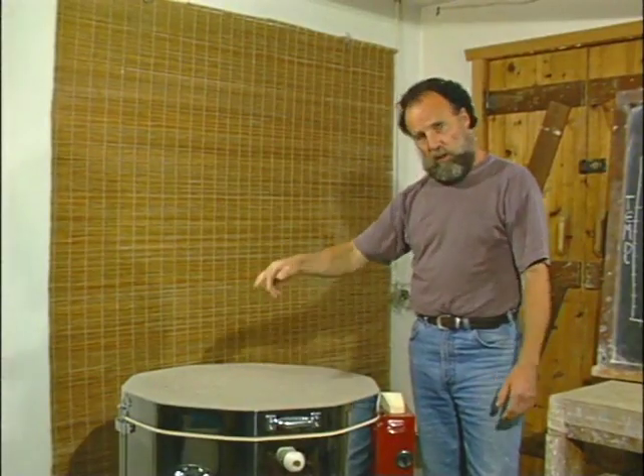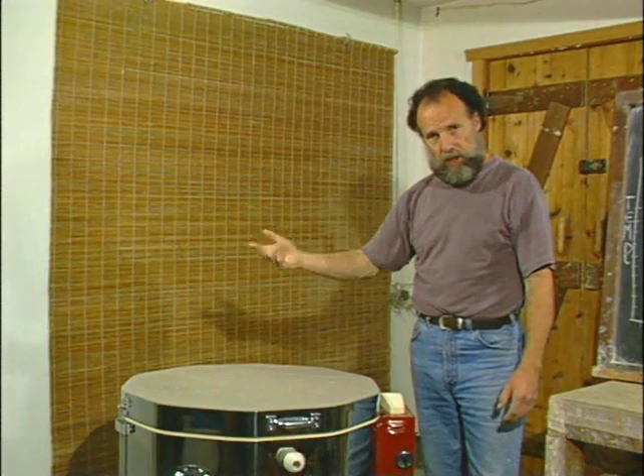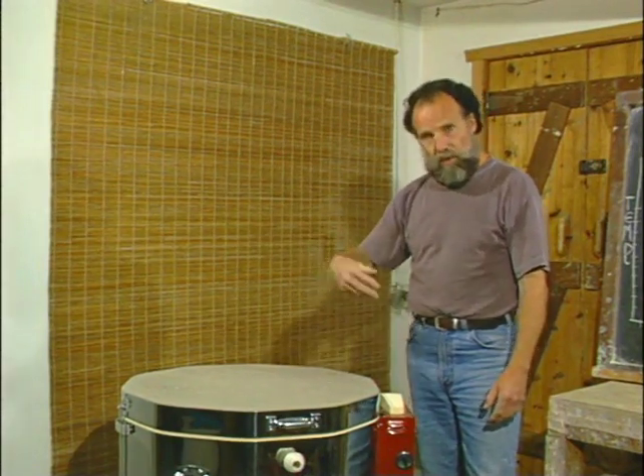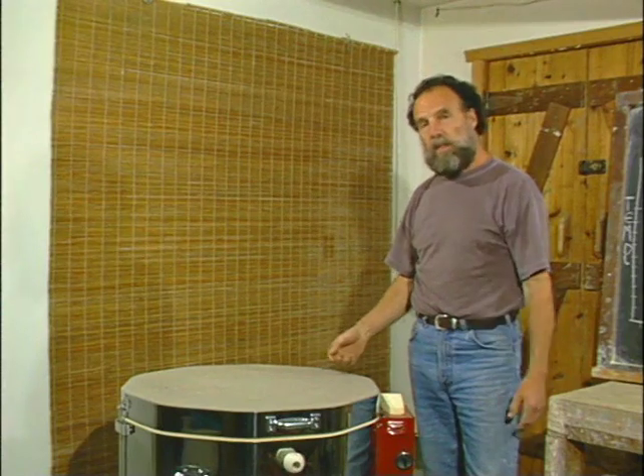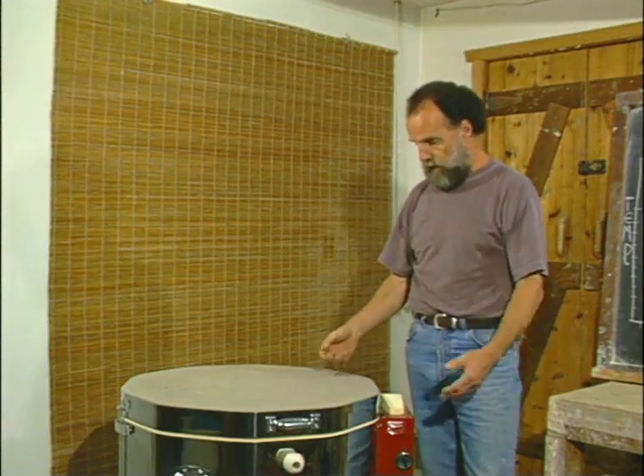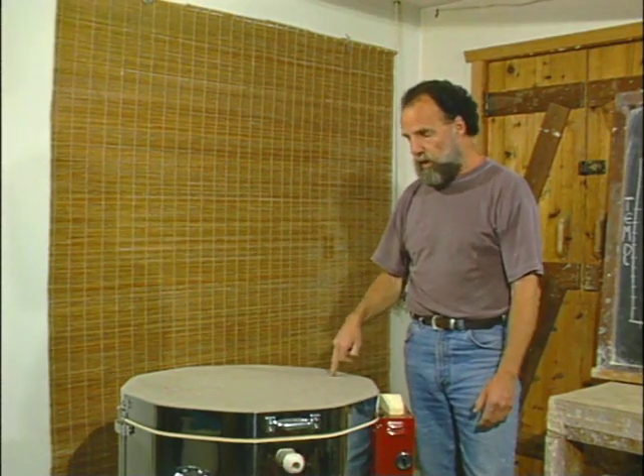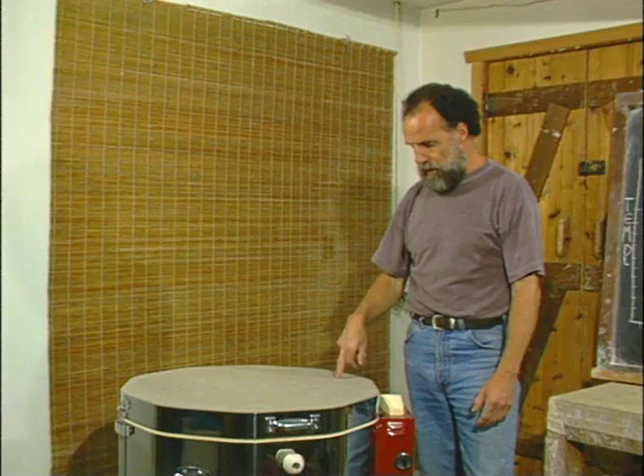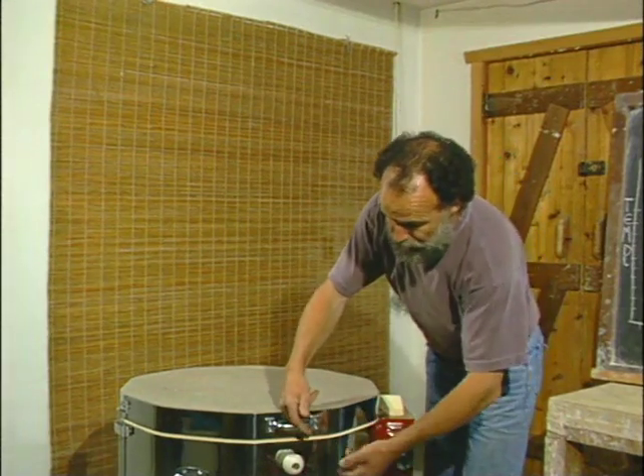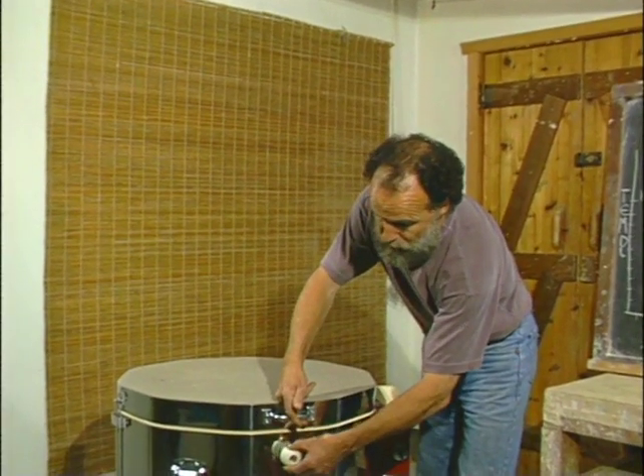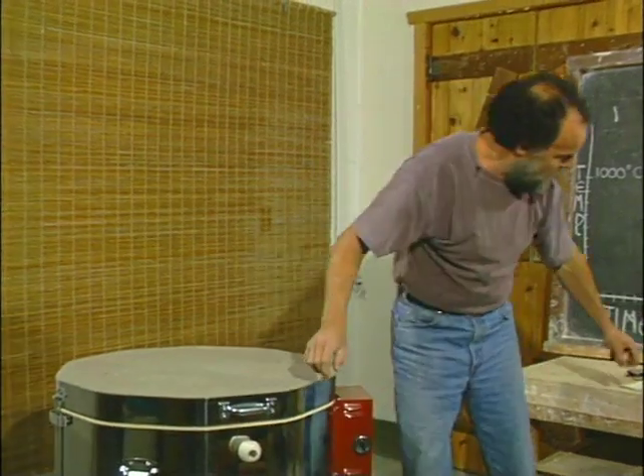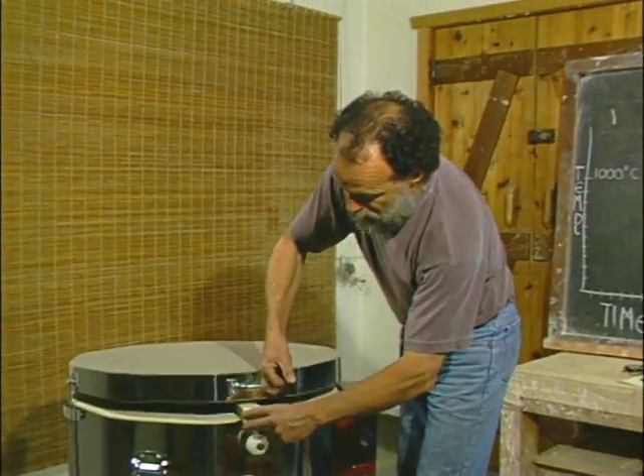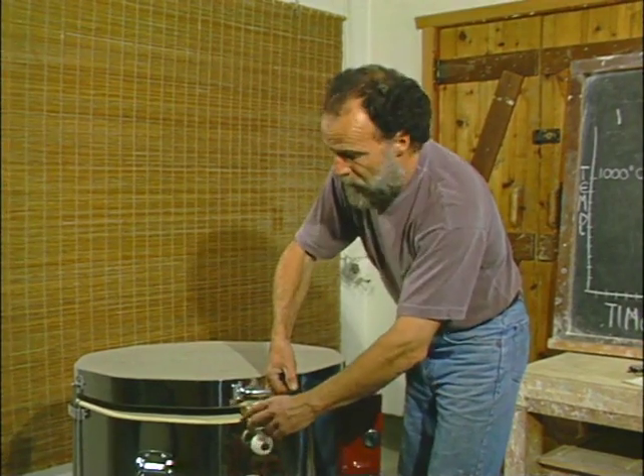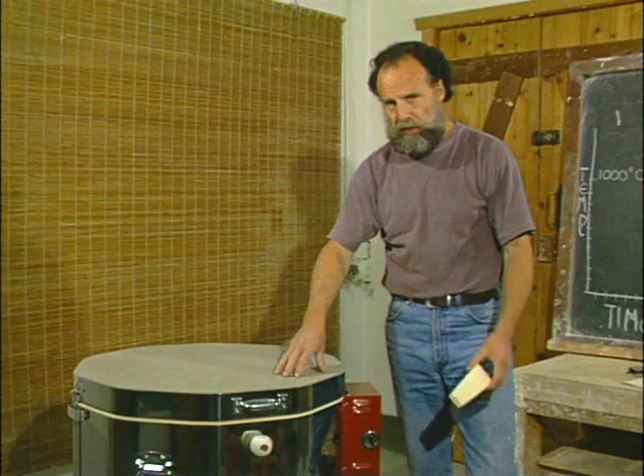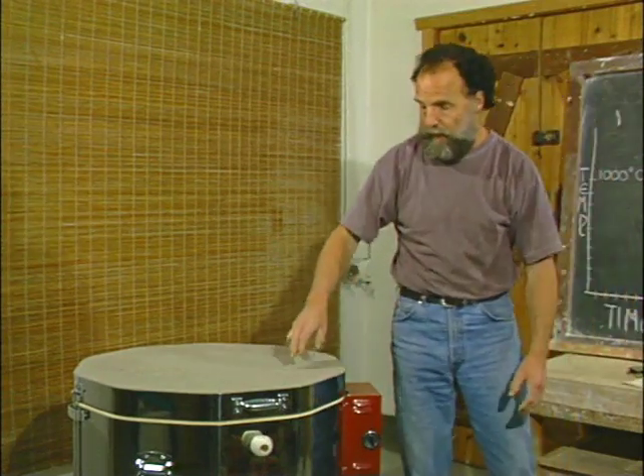As I mentioned before, this kiln is fitted with an EnviroVent, and we've switched that on and it's operating. If you don't have an EnviroVent, recall that this kiln during the firing is going to be giving off steam and some vapors which might be noxious, so you've got to be sure that it's been placed in a well ventilated area. To that end, if you're not using an EnviroVent, then certainly you've got to be able to let these vapors escape from the kiln. So at a very minimum, you'd need to leave a spy hole open. Some manufacturers ask that you wedge the lid of the kiln open during part of the firing. Refer to your manufacturer's instruction book for details on the specifics of a particular kiln.